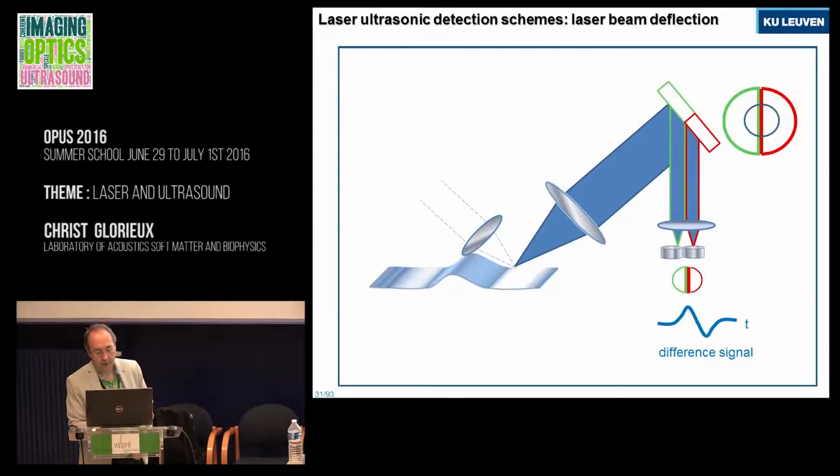Interesting, an advantage and a disadvantage, is that the wave packet here was a Gaussian, which is typical for Rayleigh waves. By the way, it's maybe strange, but when you excite a surface wave with light, you would think there's a bump moving from left to right. Actually, it's not true. It's a dip which is moving. What is happening is that you have a thermal expansion, that is a bump, but the acoustic wave is a dip that's moving away. Here it's shown a bit wrongly. In any case, the bump is Gaussian.